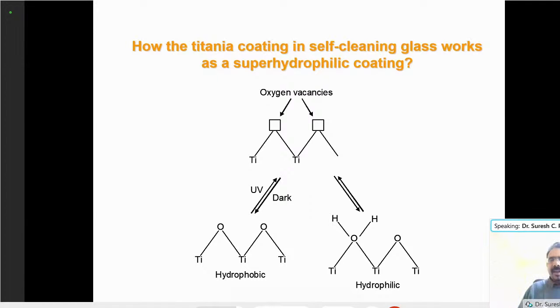So we know that titanium dioxide is TiO6 8- octahedra. So just think of it as TiO2. If the Ti4+ changes to Ti3+, what will happen? Some of the oxygen has to leave the surface in order to keep the stoichiometry. So that will create oxygen vacancies on the surface.